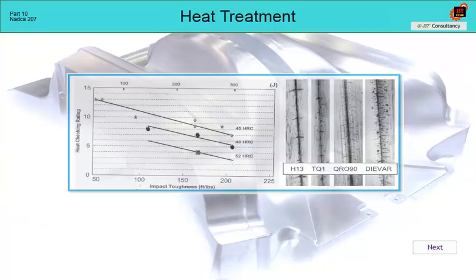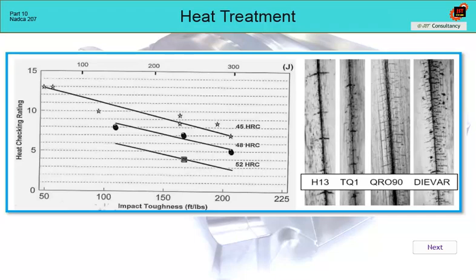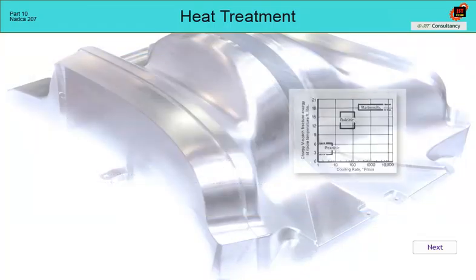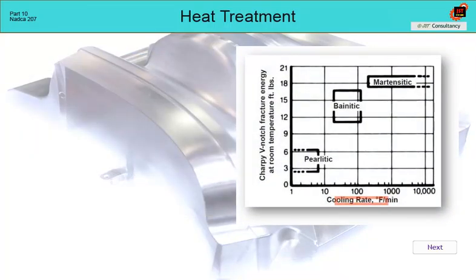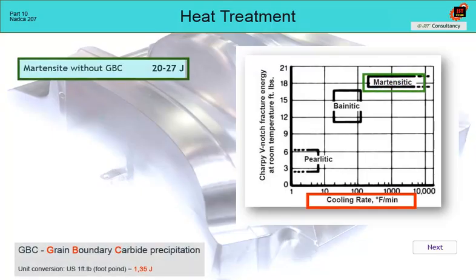Just as the purity of the material, the amount of primary carbides or the grain size has a major effect on the impact strength, there is also a correlation between the impact strength and the internal structure of the steel after quenching. It can be seen from the figure that, depending on the cooling rate, different structures can be achieved in the material. Each of these structures has different properties, including toughness. To maximize it, we must be sure that after quenching we have a martensitic structure, not bainitic or perlitic.